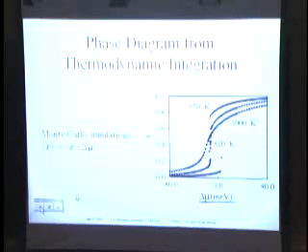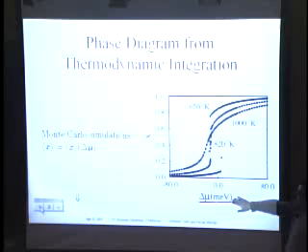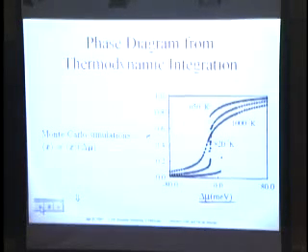You keep switching atoms from gallium to indium, or from indium to gallium. Each of these switches will have a certain energy cost that is weighed with the Metropolis factor, and in this simulation, at a given pressure and at a given chemical potential, after millions of sweeps, millions of trials in which you try to change a spin variable from +1 to -1, you do this over and over again, and you end up with a point that tells you what is the concentration of, say, gallium 0.9 for a given chemical potential. And you repeat this over and over again.